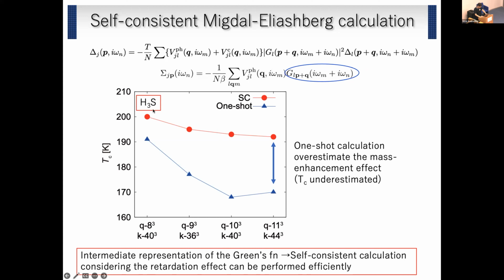because this is a result for hydrogen sulfide, and we do a one-shot calculation. Namely, if we calculate the self-energy in a one-shot calculation, starting with a non-interacting Green's function, then TC is a bit underestimated. And if we do a self-consistent calculation, then TC becomes closer to the experimental value. But anyway, if we use an intermediate representation of the Green's function, then the numerical cost to solve this Eliashberg equation becomes very cheap.